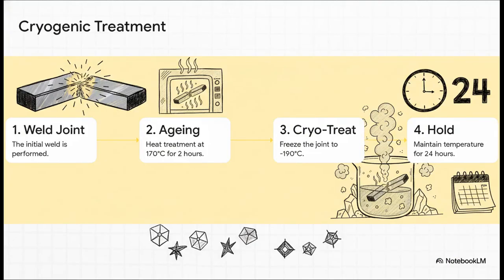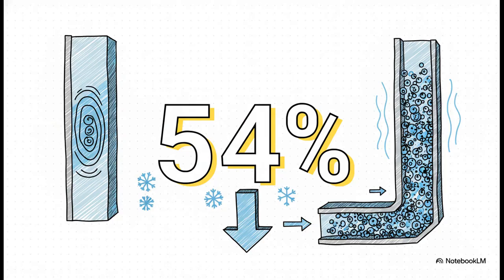So after welding a joint, researchers first gave it a gentle heat treatment, a process they call aging. And then they did something pretty extreme. They dunked the entire joint in liquid nitrogen, freezing it solid to minus 190 degrees Celsius. And they just left it there for a full 24 hours. And the result of that deep freeze? A mind-blowing 54% increase in the joint's strength.